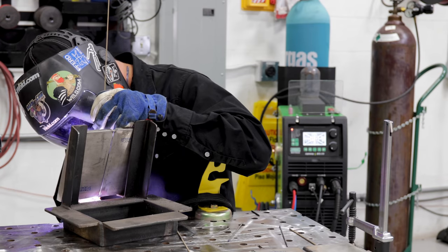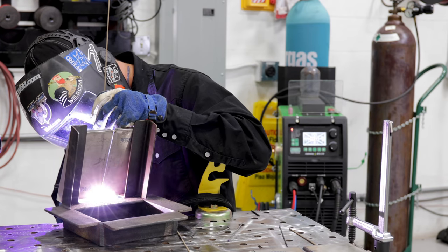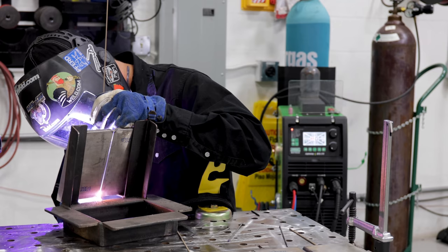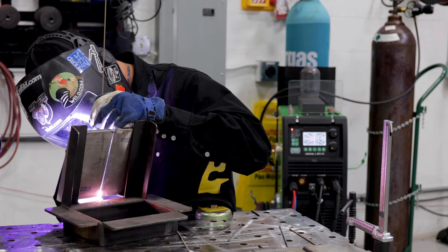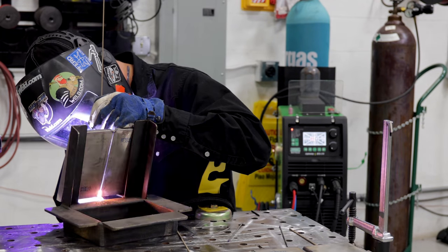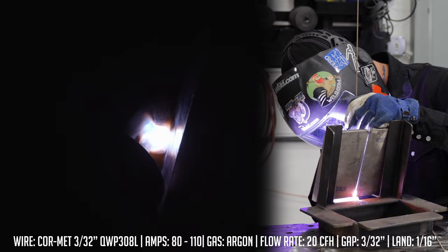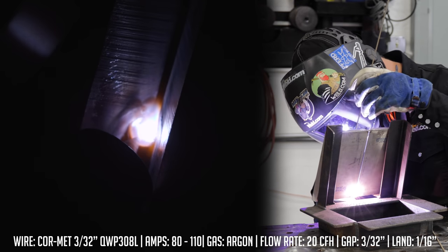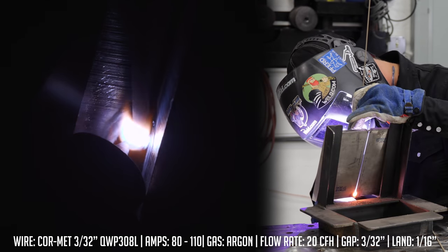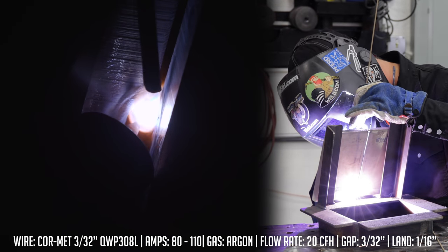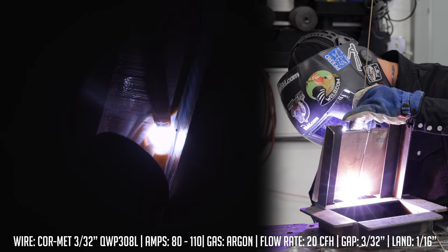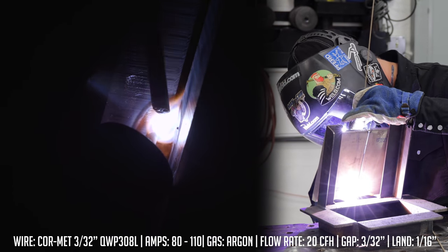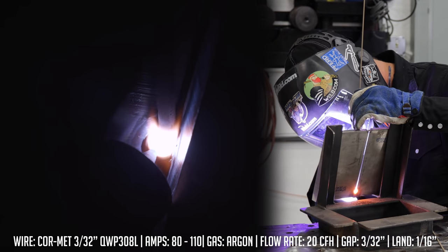The keyhole wants to go real big, get erratic, and blow out, so that land will help me control the keyhole to the size where I can weld with it and move up the joint. I'm getting a keyhole going here, pushing in, dipping the wire in, pushing it in, then resting my cup.